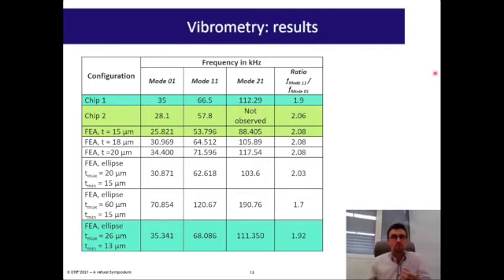From the simulation, we can learn that if the elliptic profile is important, the ratio of the resonance frequencies of the first modes is decreasing. For example, here, if the maximal thickness goes from 20 microns to 60 microns, the ratio between the two first modes will decrease from 2.03 to 1.7. So it can be a good indicator and a non-destructive test to evaluate the membrane non-uniformity.